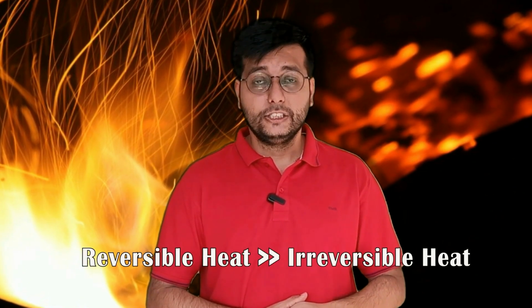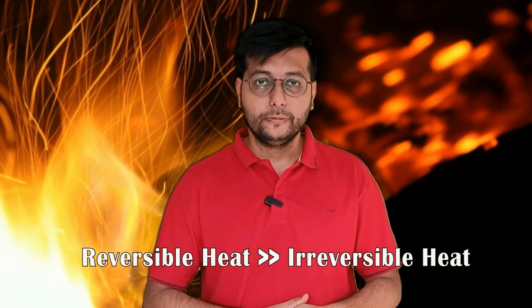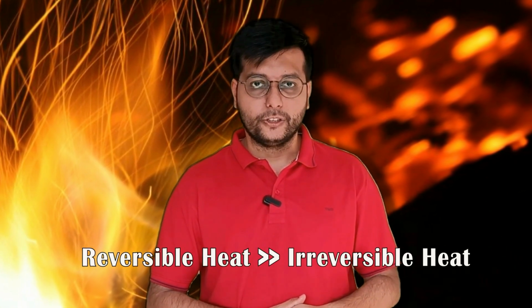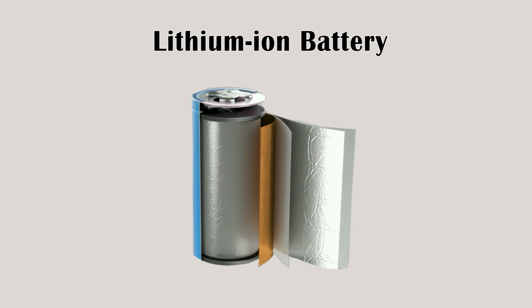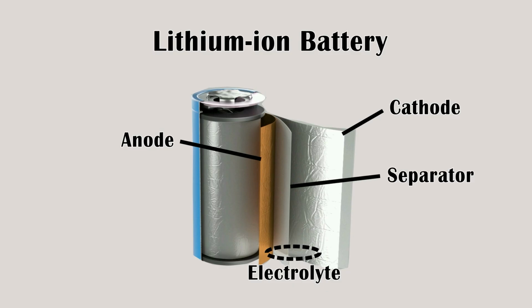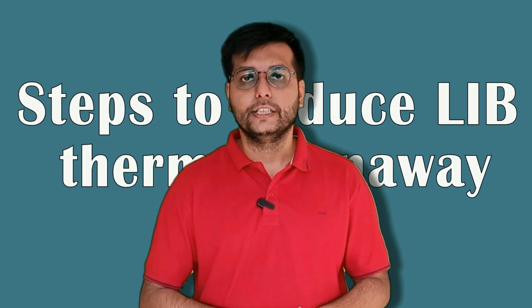or due to any other exothermic chemical reactions occurring inside the battery. Reversible heat generation is 6 to 7 times higher than the irreversible heat generation inside lithium cobalt oxide batteries. Thus, modification of the components of the lithium-ion batteries to reduce the reversible heat generation or to withstand a certain threshold temperature might be the best possible way to reduce the battery's thermal runaway. The lithium-ion battery mainly has 4 main components: the cathode, the anode, the electrolyte, and the separator. Hence, modification of each of these 4 parts may reduce its thermal runaway.